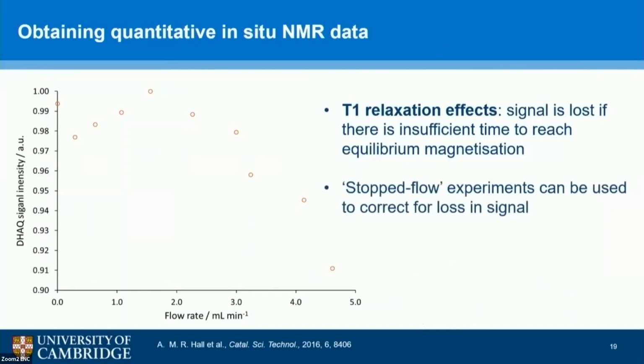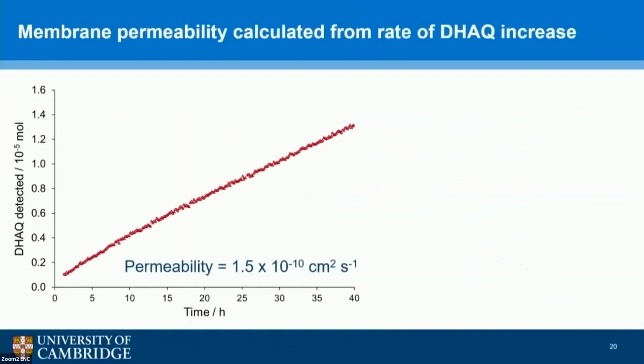However, there's a relatively simple solution to this. We can just use stopped flow experiments. This is basically where we take a spectrum while flowing the electrolyte, and then again when not flowing the electrolyte, and we just get a correction factor so that we can still obtain quantitative information. It's also important to consider this depends on the T1, so you have to make sure you're doing this for the correct T1 in that situation.